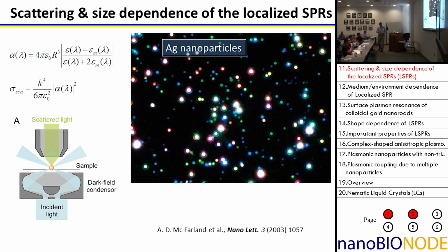The dark background is where you have some dispersing medium, a solvent of some kind, and those bright scattering objects are all nanoparticles of different size, right? And the color appearance and the brightness all depend on what precisely type of nanoparticle you have. And again, this type of observation is possible for very tiny particles, even if they are much smaller than wavelengths of light, 10 nanometers or so.